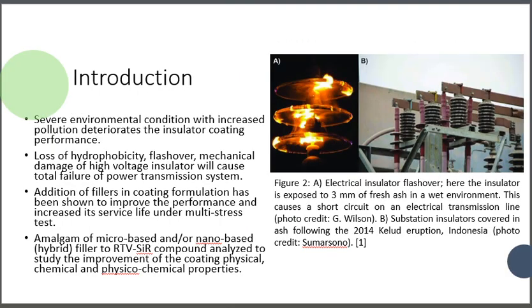Despite these advantages, severe environmental conditions can significantly reduce the performance of insulated coatings. In regions with high pollution levels such as coastal, industrial, or volcanic areas, contaminants accumulate on the insulated surfaces. This contamination can lead to loss of hydrophobicity, surface leakage currents, electrical flashover, and mechanical degradation of the insulator. These failures may ultimately lead to power transmission interruptions.